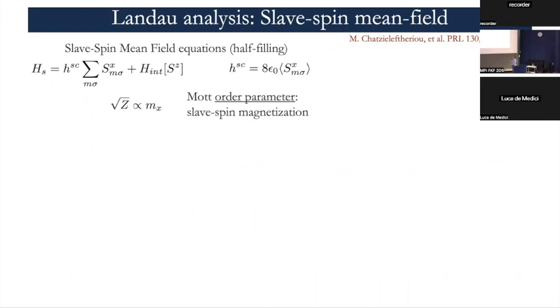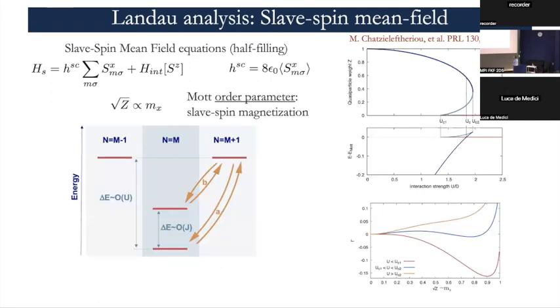to study the competition between the stable and unstable solutions, and you can do that in slave spin mean field, in which this Mott transition is portrayed in an auxiliary system of spins as a ferromagnetic to disordered transition. So the order parameter is the magnetization of these slave spins, which is equivalent to the square root of the quasi-particle weight. And you can show through the Landau analysis of these slave spin equivalent equations that the discontinuity, so the first order character, is due to Hund's coupling.